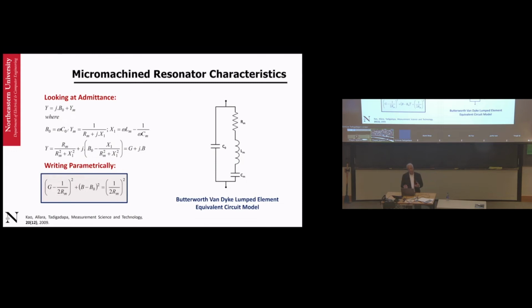And piezoelectricity comes from the fact that these are crystals with a particular structure whereby there is an imbalance in the charges of the positive and the negative ions inside the molecules. We just can't get the C-axis of the quartz to align when we deposit. We can grow the crystal by the traditional methods, but we cannot put it as thin films. It's quite different from aluminum nitride, which we also knew, but 20 years ago, we were able to develop a process by which we can actually deposit aluminum nitride in piezoelectric fashion. But anyway, I will not go into aluminum nitride for the moment. Let's just stay with quartz.